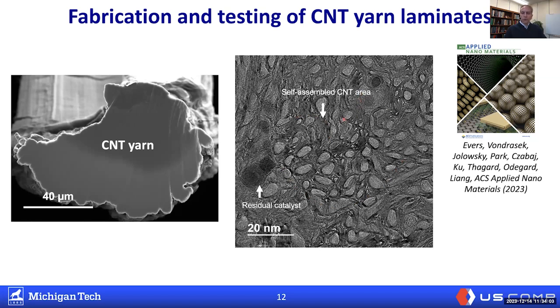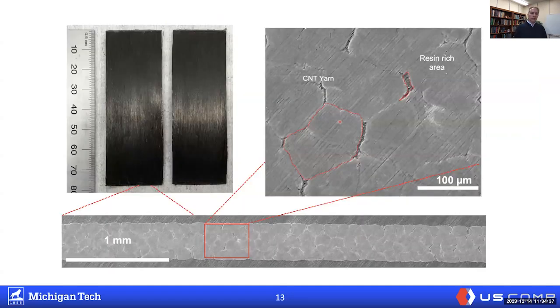And put together, this forms a carbon nanotube yarn, which has some pretty remarkable properties compared to carbon fiber, not only in terms of stiffness and strength, but one of the major advantages of this type of microstructure is the flexibility of the yarns. Whereas carbon fibers, if you bend them too much, they will snap. They're brittle enough to do that. These carbon nanotube yarns, they don't like to snap. When you bend them, they like to just bend. So we can make all kinds of really interesting woven patterns or preformed patterns using carbon nanotube yarns, which is a big advantage.